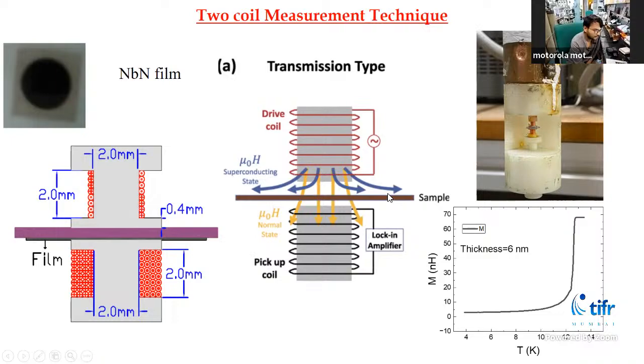But below its TC, when it becomes superconducting, it is repelling. I am showing here with the blue thick lines. It's repelling most of the magnetic fields, so the pickup coil here will pick up a very small amount of magnetic field. You can see here below TC, it goes directly down and is very negligible for our measurement. So here are the two techniques: one is the resistivity measurement and the other is this two-coil measurement technique. With these we can establish that our superconducting films are being formed.